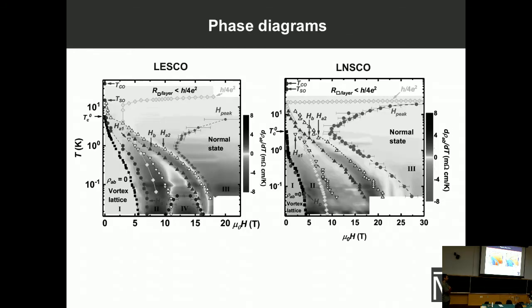So yes, this supports these being the real phase diagrams. And I don't have time to go into details. But basically, we have measured anisotropic transport, and we find that in this high field regime, beyond what we identify as the upper critical field, it does not depend on the field, and it has the value that is basically the same as the value at high temperatures. So which supports our conclusion that we are in a normal state. And then the red points are the results from the anisotropy. So we start seeing the anisotropy as we start getting superconducting fluctuations.